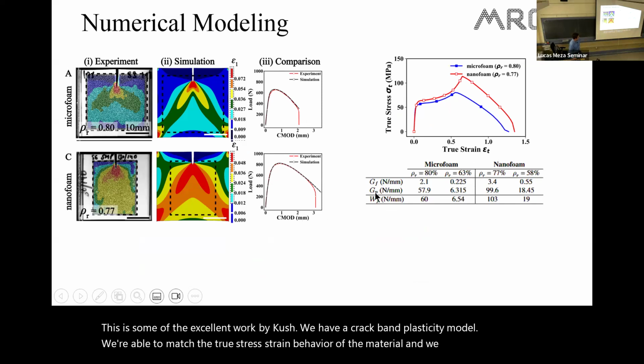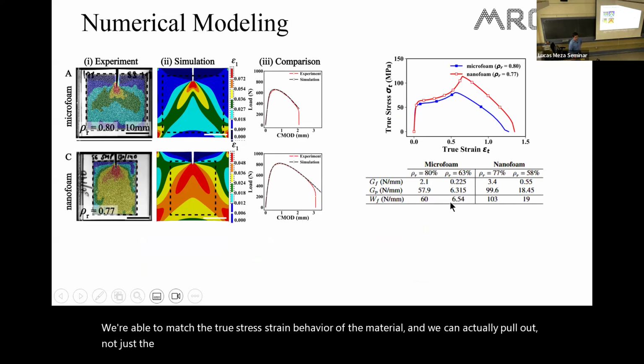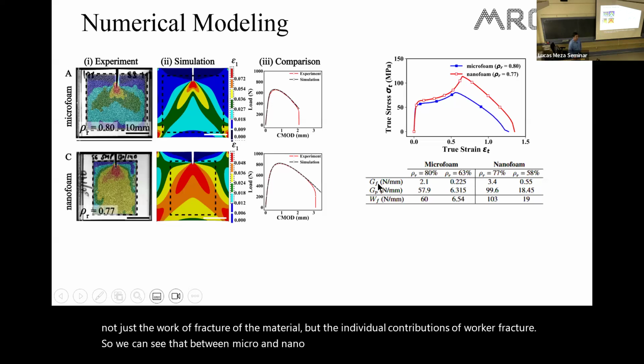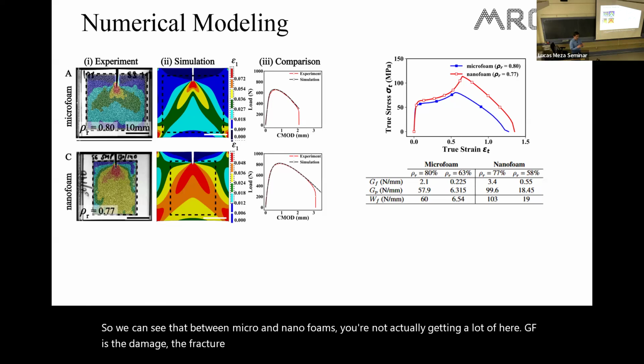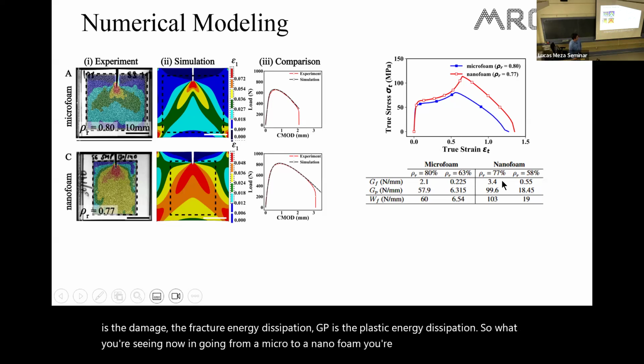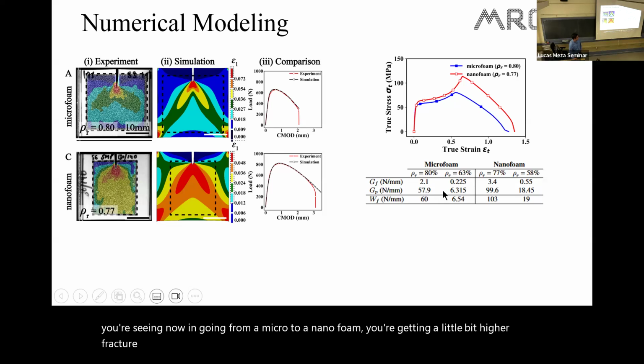And we can actually pull out not just the work of fracture of the material, but the individual contributions to work of fracture. GF is the damage, the fracture energy dissipation, GP is the plastic energy dissipation. So what you're seeing in going from a micro to a nanofoam is a little bit higher fracture energy dissipation, but double the plastic energy dissipation.